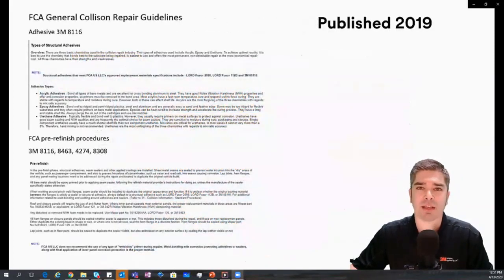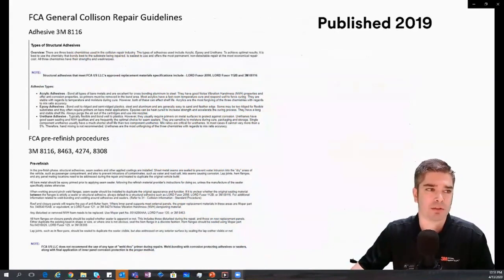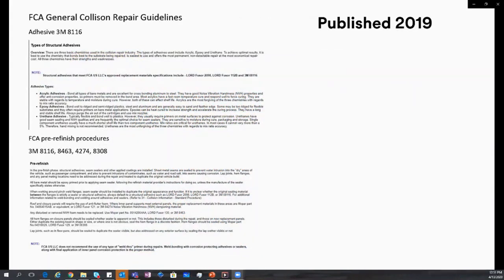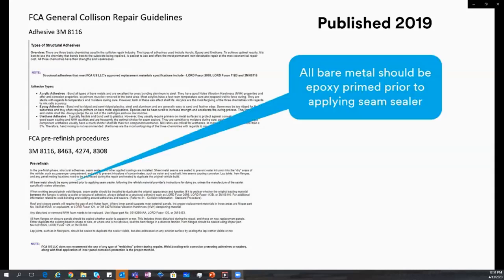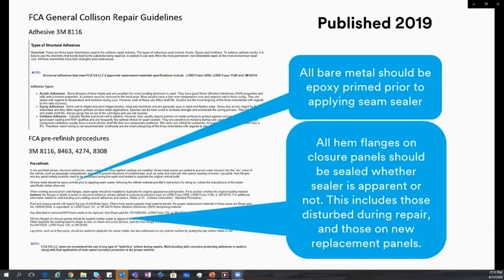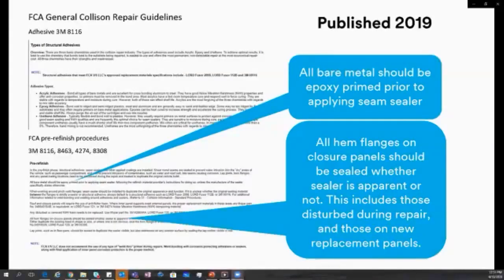So this is a Chrysler bulletin. It was published in 2019. It was updated. This is their refinish repair guidelines, and I want to highlight the bottom down here where it says pre-refinish repair guidelines, because they also make mention that all bare metal should be epoxy primed prior to applying seam sealer, right? They also go on to say that all hem flanges on closure panels should be sealed whether sealer is apparent or not. This includes those disturbed during the repair and those on new replacement panels.